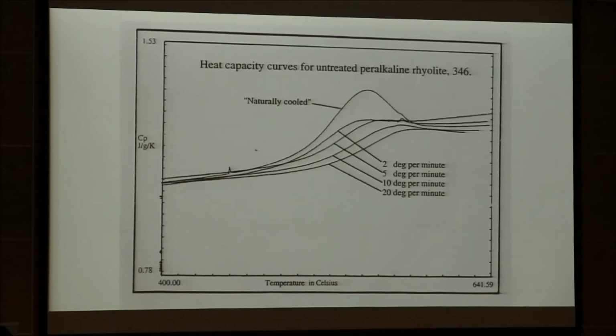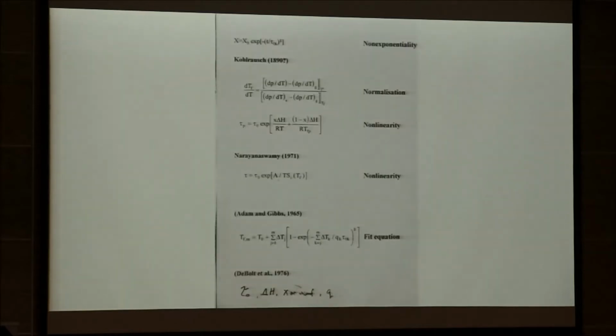Now, unfortunately, the range of cooling rates that the calorimeter will endure has limits on the slow side of signal intensity, and it has limits on the fast side of temperature gradients. Anybody who's done any calorimetry knows there's only a certain set range of rates that you can use any particular type of calorimeter for. They limit what I can do for a calibration, but they allow me to calculate out the material-specific parameters that I can use to estimate what this cooling rate was. So simple as that, okay? But actually the practical trick, which made it all possible, was simply thinking about how we could get this calibration good enough that we could use it for determining natural rates.